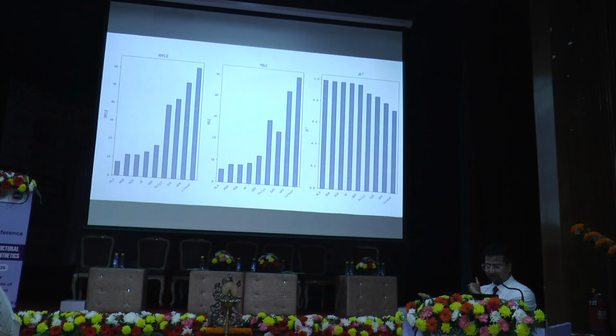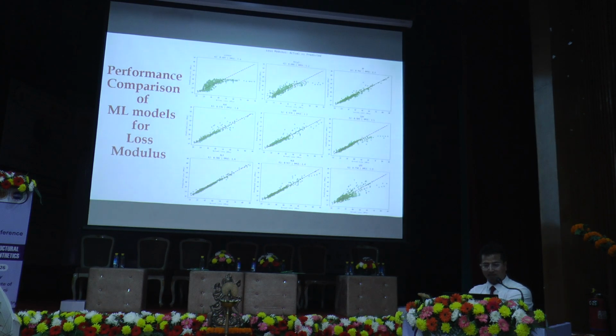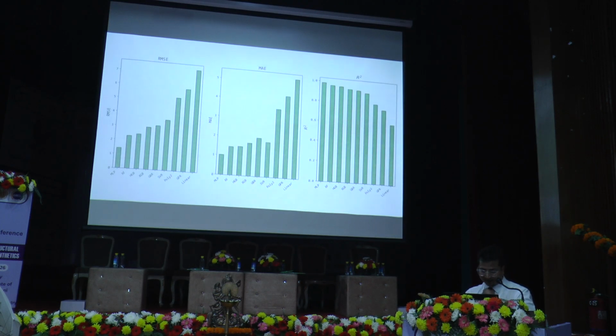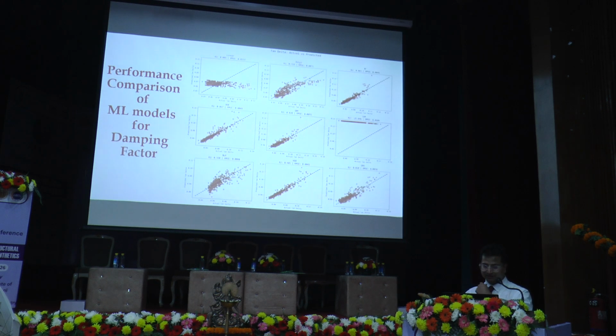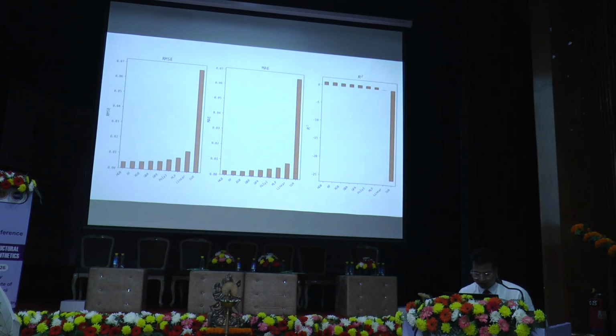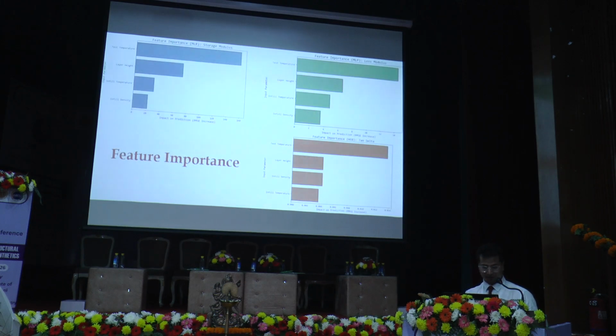As you can see, 0.99 R-square value for the MLP. Similarly for loss modulus, MLP gives the highest R-square value, so I chose MLP for loss modulus as well. For tan delta, you can see that in several models the data is not plotting well on the 45-degree line. So for tan delta, I chose HGB, which is a histogram based gradient boosting regression ML model.